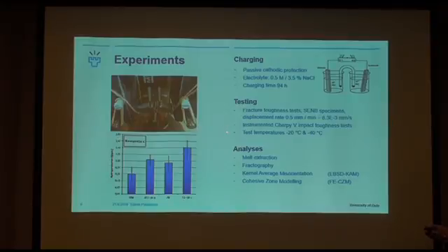We used melt extraction to define the total hydrogen contents in uncharged and hydrogen charged conditions. And the results show two distinctive levels in both microstructures. Fractography to identify the hydrogen embrittlement related features. Then kernel average misorientation to measure the degree of lattice deformation or distortion. And cohesive zone modeling to test its applicability to these conditions and to model and expand these tests even further.